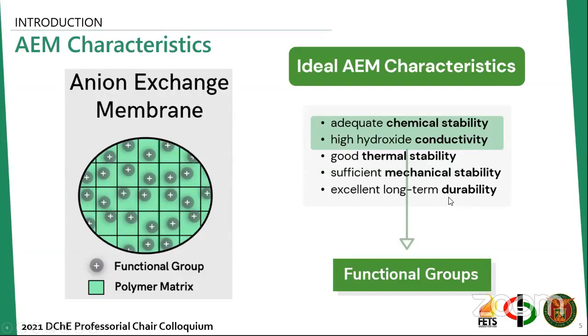Among these criteria, high hydroxide ion conductivity and chemical durability have been considered the most important properties for use in practical systems. These can be attained by choosing suitable functional groups for the AEM. The polymer backbone is mainly responsible for the thermal and mechanical stability. So at this point, we want to address the low hydroxide conductivity and poor long-term alkaline stability of AEMs, which are their major limitations.